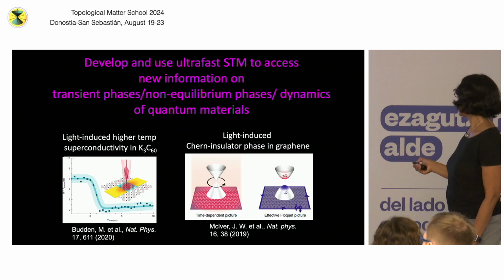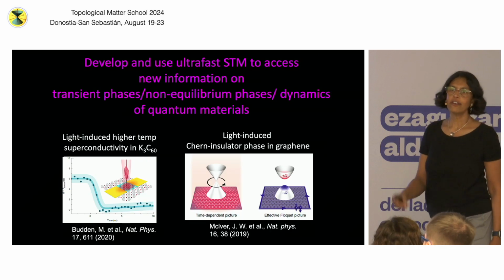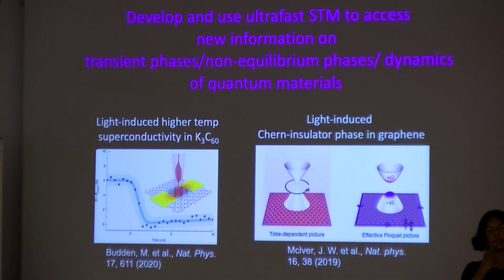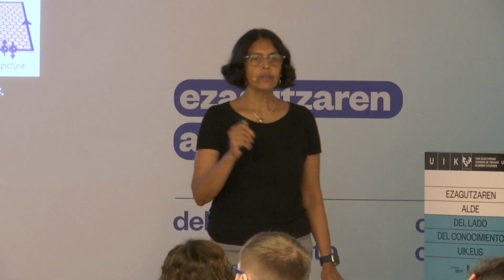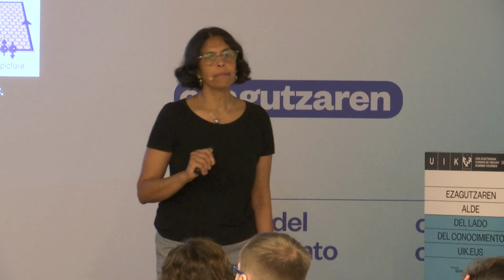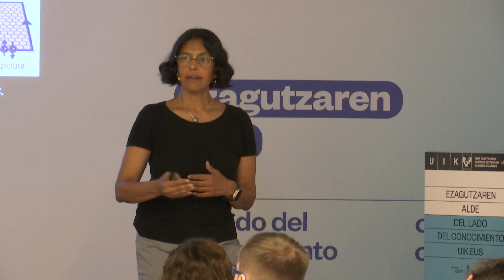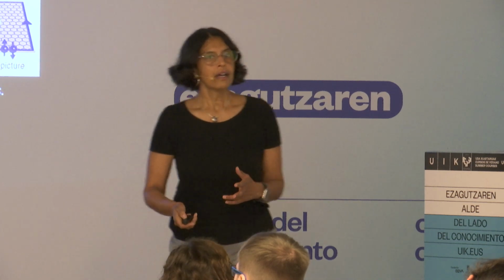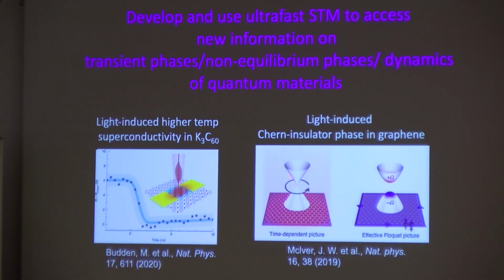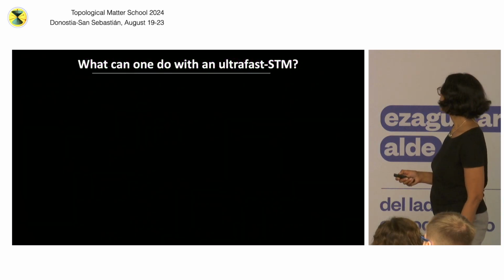And there are many other phases you can realize. One interesting thing about light is that circularly polarized light breaks time reversal symmetry. So you can use it to break time reversal symmetry in a material externally without applying a magnetic field. So that then you can imagine having a Dirac cone like this, applying circularly polarized light, gapping out the Dirac cone, and then realizing edge states. Okay? So those are very cool uses of light.